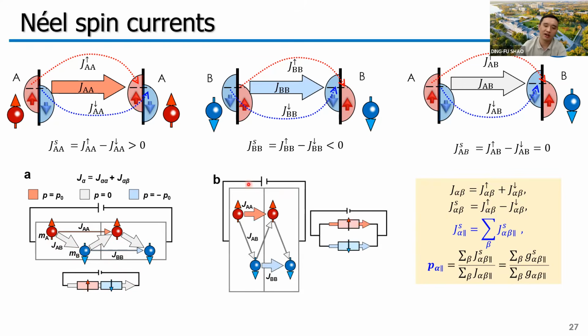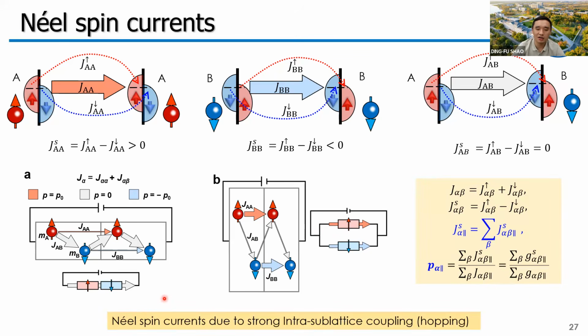But if we have such antiferromagnets where the AA and BB distances are small, but the AB distance is large, then JAA and JBB are much larger than JAB. We can then simply consider these antiferromagnets as two ferromagnetic sublattices connected in parallel. In this case, even though we only have a globally spin neutral current, within the sublattices we can have staggered spin currents. We dub this staggered, sublattice resolved spin current the Néel spin current.